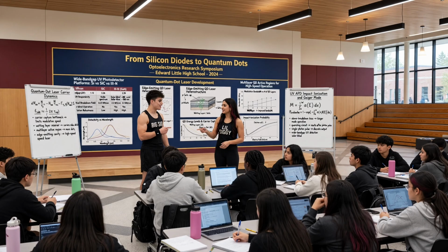Oh, and because our viewing laser was tuned perfectly to the original uncharged energy level. Exactly. The trapped electron detunes the system, it quenches the exciton transition. The dot essentially goes blind and deaf to that specific laser frequency. The scientists are watching their monitor, seeing a bright, steady signal, and then snap, the signal drops completely to 0. That instantaneous drop is the exact moment the single electron was captured. That's profound. They're watching a single artificial atom capture a single electrical charge in real time just by watching it blink out. And it stays dark until that captured electron eventually manages to quantum mechanically tunnel back out of the dot into the surrounding charge reservoir.